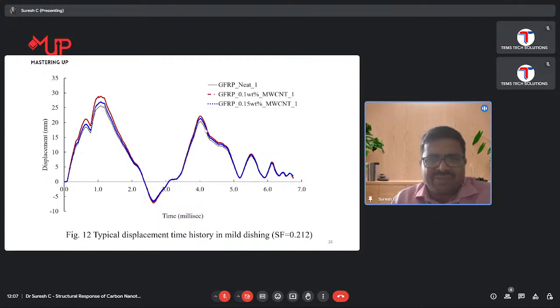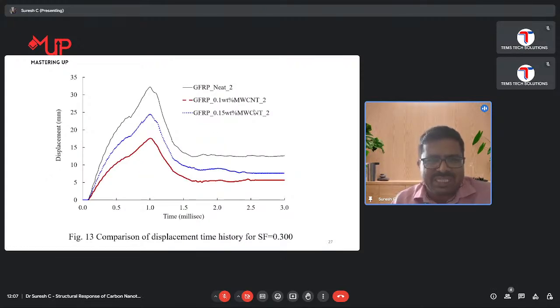This is for 5 gram charge weight for all the three plates, how it behaves. We have 0.1 weight percentage and 0.15 weight percentage of the carbon nanotubes. Second, the same experiment is repeated for 10 gram composites. In 5 gram, we could not see much difference between neat, 0.1 and 0.15 weight percentage of composites.